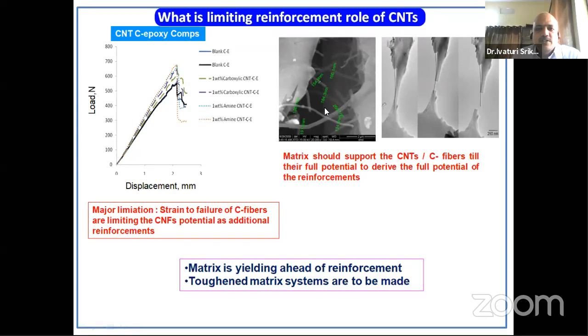But when you actually add CNTs to the carbon fiber reinforced composites, there is absolutely no improvement at all, initially. The reason is, you can see here, the matrix systems that we are using are very brittle in nature. You can see here, the nanotubes have not yet failed. This is our own image, and this is the image from the literature. The matrix system is failing ahead of the nanomaterials. Nanomaterials, as I told, have about 10% elongation. In one of the slides, I showed a comparison with carbon fibers of the percentage elongation. It has a very high percentage of elongation, but the matrix system is failing ahead of the nanotubes, because matrices used for structural applications are very brittle in nature, with a 2 to 3% strain to failure.